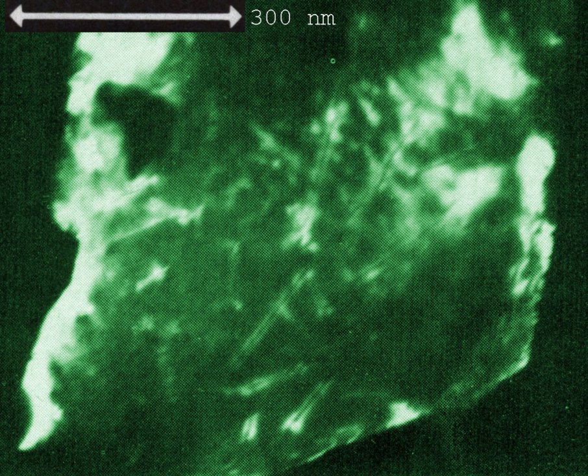High electrical resistance: non-conducting dielectric minerals, glasses, and polymers have this property, while highly conducting metals and alloys do not have this property. In metals, the thermal diffusivity is coupled with the electrical conductivity, suppressing the formation of a thermal spike. High radiation sensitivity: polymers have high radiation sensitivity as compared to glasses and ionic crystals. The radiation effect in polymers is caused by the secondary electron cascade, inducing both chain scission dominating in the track core and cross-linking dominating in the track halo.